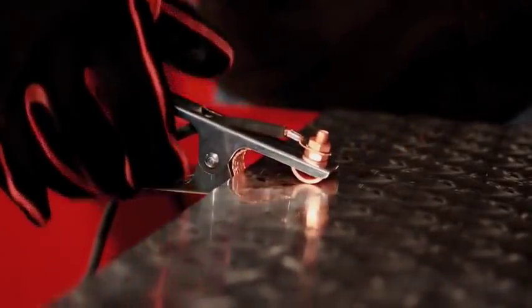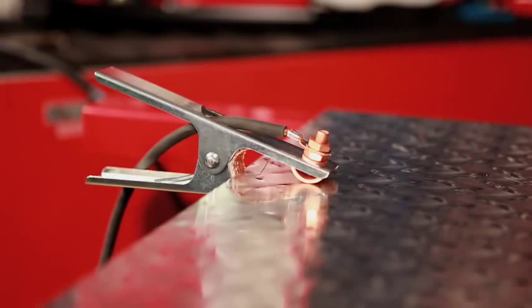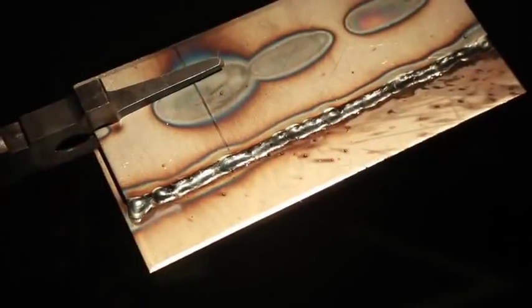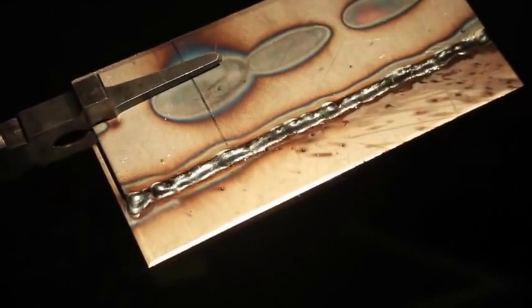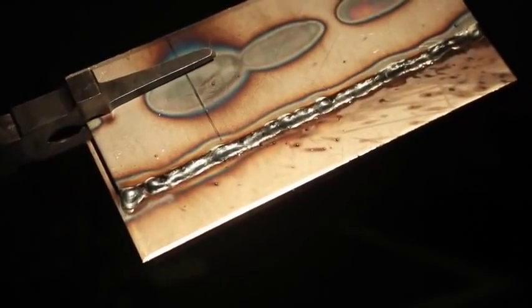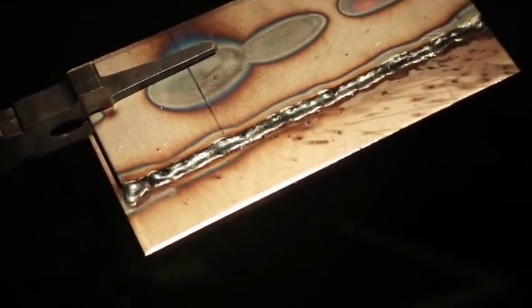The most common mistake of beginning wire welders is not fully completing the electrical circuit with a sound metal-to-metal connection. Without a completed circuit, there will be no arc. Beginners also tend to weld too fast. The result is a thin, uneven bead and poor penetration. Poor penetration creates a weak weld, prone to failure. With proper penetration, the weld will actually be stronger than the base metal.